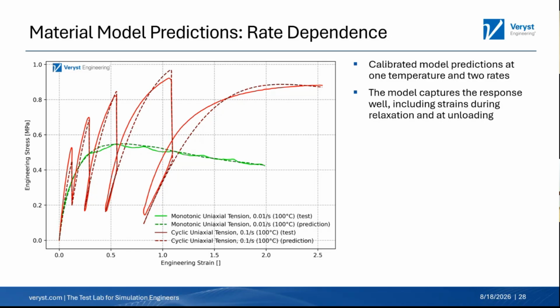The hysteresis is when we do that unloading, say on that red curve at about 100% strain. When we unload, we don't exactly follow the loading path back up. That's some hysteresis. We're not quite capturing that, but overall, I'm very happy with this model. We're capturing the large strain response of this material, the rate-dependent response, and we're doing it accurately here. This is a well-calibrated model.